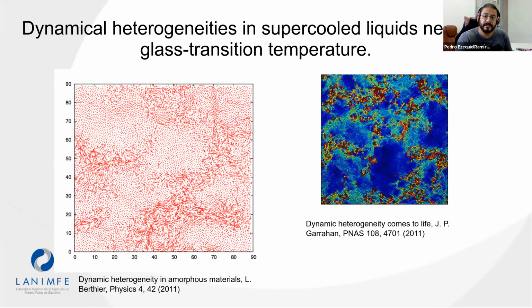Dynamical heterogeneity is another essential feature of disordered materials which emerged from experimental studies of viscous molecular liquids near the glass transition. In these systems, local relaxation is measured by mechanical or dielectric probes, showing a wide range of non-exponential relaxation times. Indeed, using computer simulations to study supercooled liquids, we can observe that the density fluctuations expected in the fluid become observable near the glass transition temperature. In contrast with equilibrium liquids, where density fluctuations relax at inaccessible time scales, near the glass transition the relaxation time grows enough to be observed. Essentially, dynamical heterogeneity refers to the presence of different local mobility in different regions of the system, which is observed as an inhomogeneous local density inside the system.